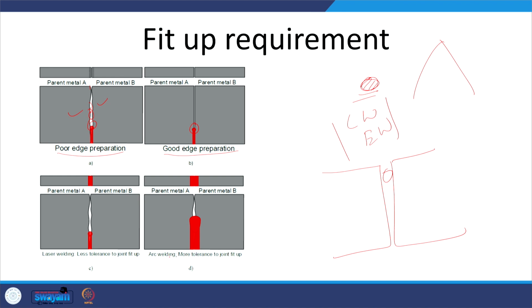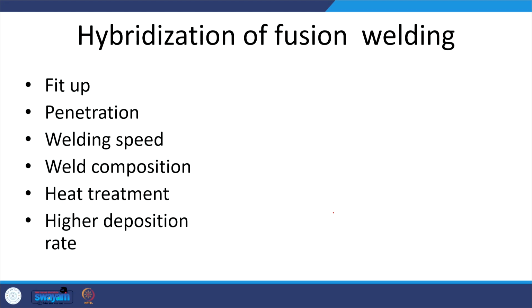But when we club the arc welding with the laser or electron beam, then heat is delivered over a larger area. So, this fit up problem is minimized. Even if the edges are rough, the heat delivery over the wider zone will facilitate the melting of the faying surfaces. Here the laser will help in realizing the deeper penetration, and the arc will help in realizing the wider bead. So, the wider bead helps in reducing the fit up requirement, and the deep penetration will be realized through the laser welding. So, the fit up requirement and edge preparation requirement are minimized when we combine the laser with the arc welding process.